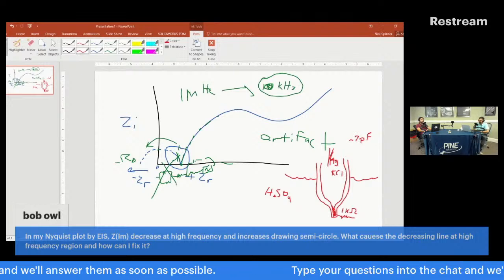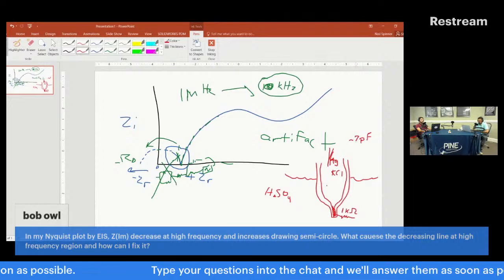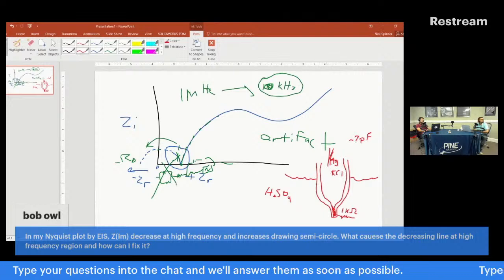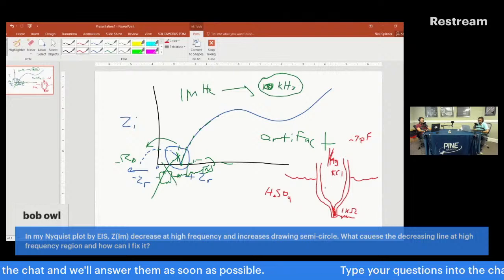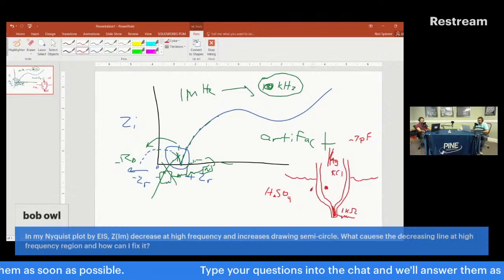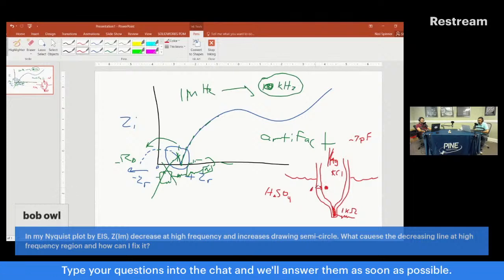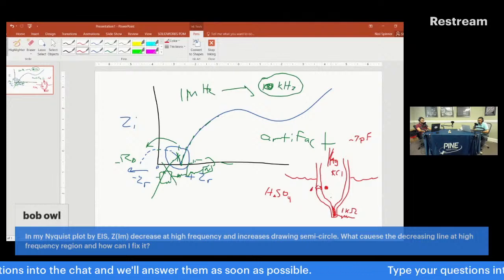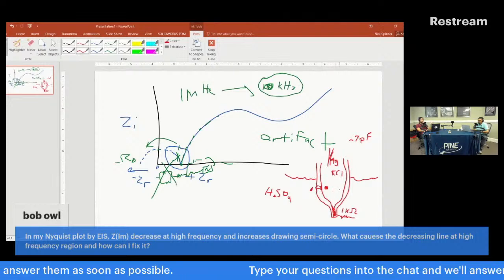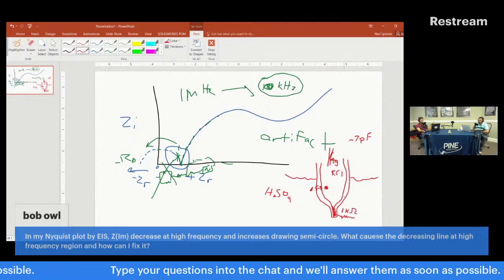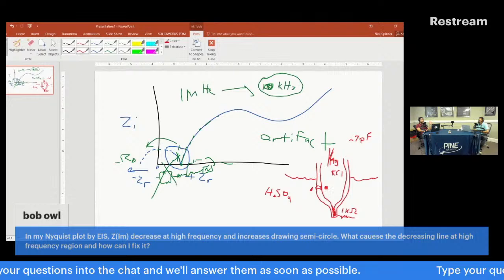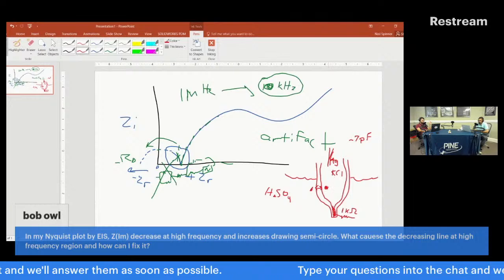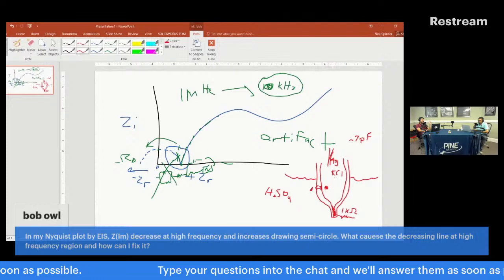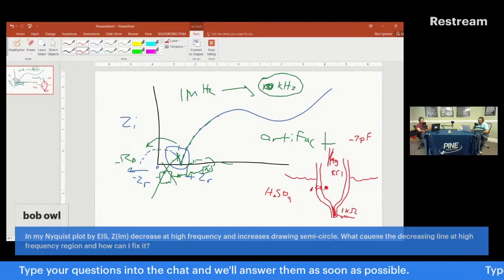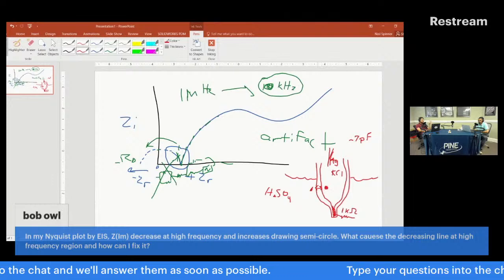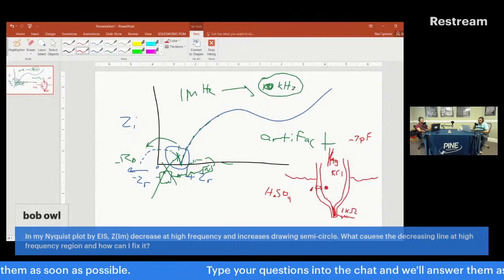Where does this come from? What does that even mean? It comes from the glass. So there is actually this situation where you have electrolyte on this side, electrolyte on this side, and you have this separator, which is the glass. Glass is a very poor dielectric material, but it is a dielectric material. It has a dielectric constant and everything. So technically, there is a capacitance between the inside of the reference electrode and the outside. Now, you'll notice one big problem with that is there is no physical communication. Electrolyte can't go through glass. It's impenetrable.